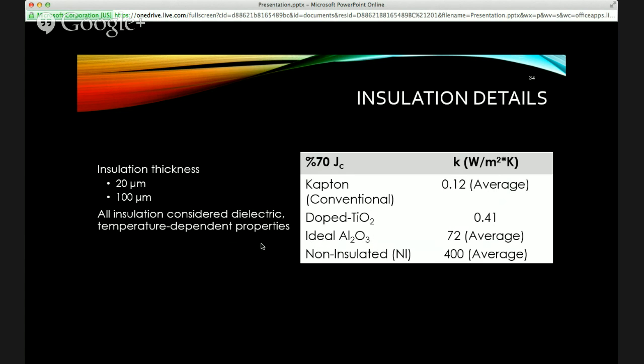The reason for this is that we want the thinnest insulation possible, but still have it function, because of magnetic packing factors. Smaller is better: the more conductor we can get into a system means more current flow, faster current flow, and higher magnetic fields if you need that. So you want to account for that magnetic packing factor, and that's where the thin insulation, the 20-micron case, came from.